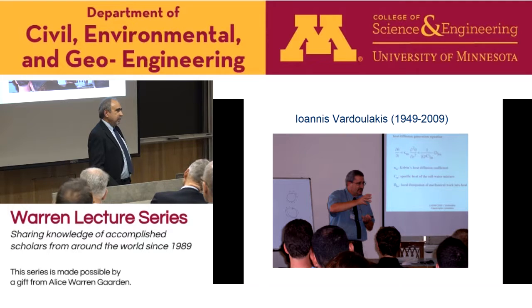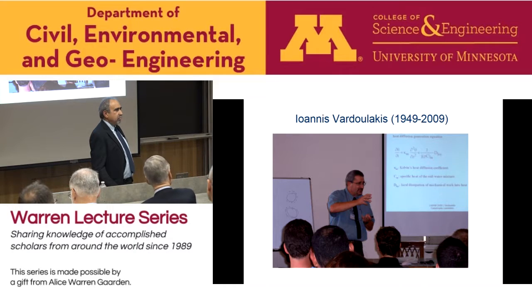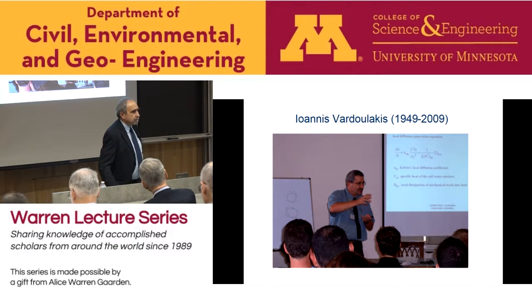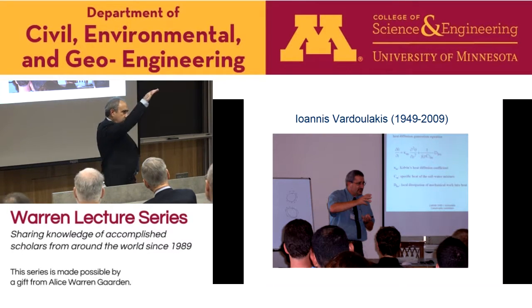Do you have any insight on that? So basically, if you do this without cohesion, fracture in sand, for example. Yeah, but there's very little toughness. No, let's say that toughness equals 0. Then there's no length in that material. Toughness, but then we talk about apparent toughness. So you have this plastic zone. My question is, what scales the size of the plastic zone? What scales the toughness? Does it come to a constant value, or does it keep increasing? If you imagine the fracture, I think it tends to a limit value. This is what I believe.